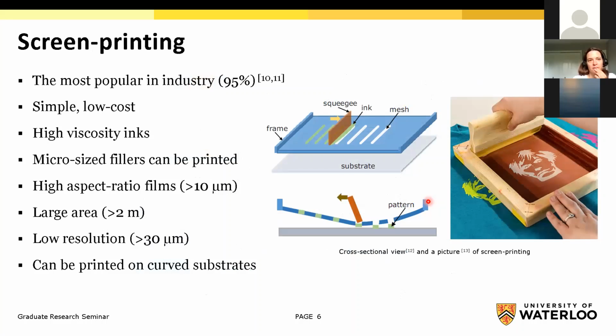You can print even larger than 10 micron. For inkjet printing, you need to print multiple times, at least 5 times, to have a thick film. But with screen printing, it's very simple. With just one sweep of the ink, you will have a 10 micron film. So that's the advantage. Yeah, that is good, because the higher, I mean, it's confusing to me talking about thickness, width, and height. But yeah, the higher the height, the more conductive the lines are going to be. So yeah, that is good.